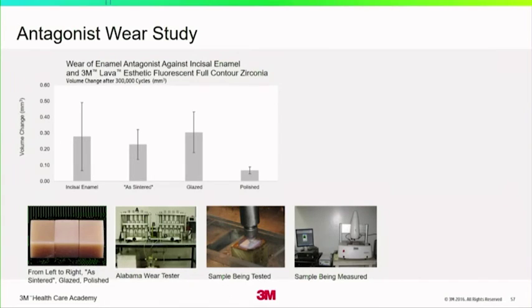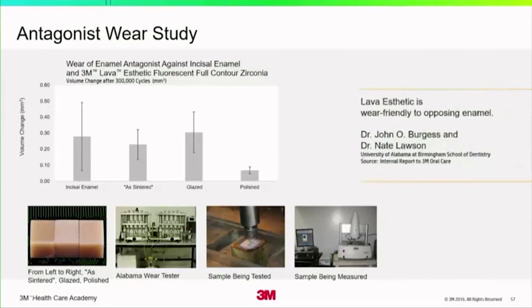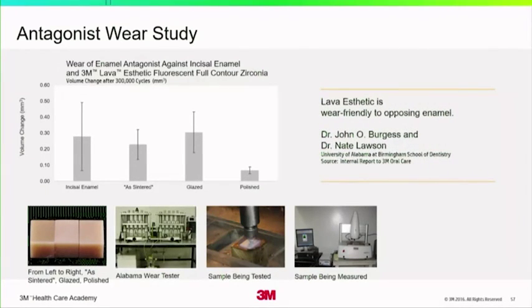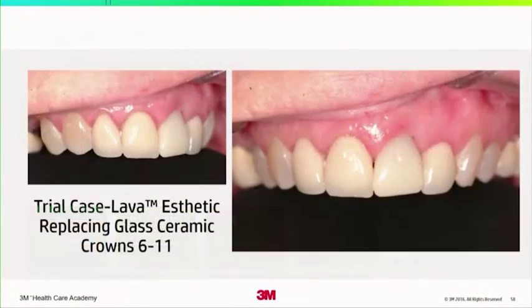And what we know about antagonist wear is no different than what we know about zirconia in general. It's very favorable. The polished surface seems to be the way to go. So if you're going to work with your lab on this, surfaces that come in contact with teeth or antagonists, if you will, of any type of material, I would prefer them polished. And in general, unless staining needs to be done for a particular reason, because you just can't get the right things, like, for instance, some fluorosis or some decalcifications, those can be externally applied, but generally only for a cosmetic improvement. And John Burgess at the University of Alabama concludes that this material in the polished state agrees with the studies that we have seen earlier in this presentation.